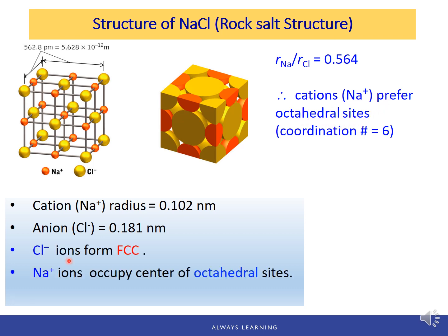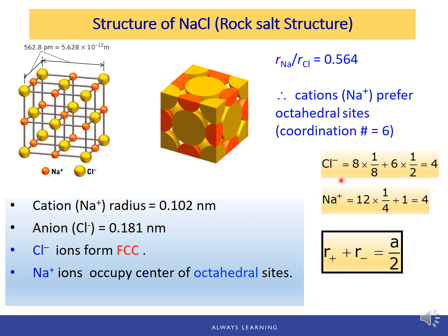Therefore we can see the structure as the anions forming an FCC structure, with the cations occupying the center of the octahedral sites. From this FCC crystal structure, we can also get the number of anions and cations in the unit cell. For the chlorine anion, we have 8 corner ions and 6 face ions, a total number of 4 anions in one unit cell.